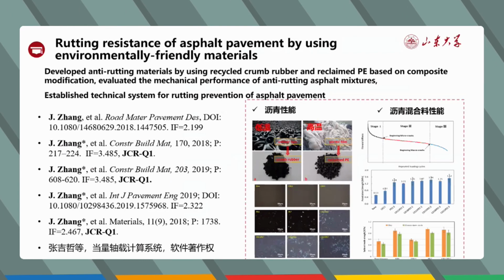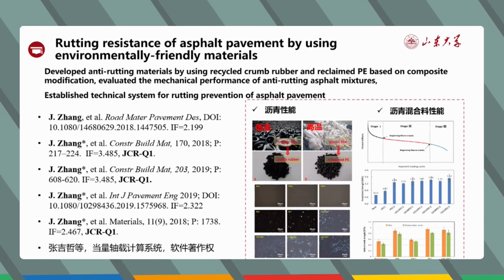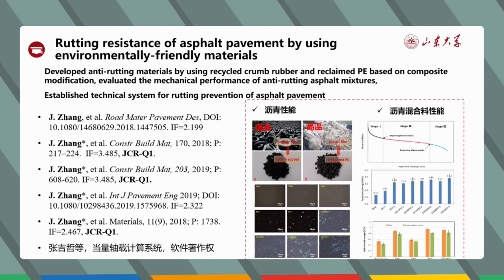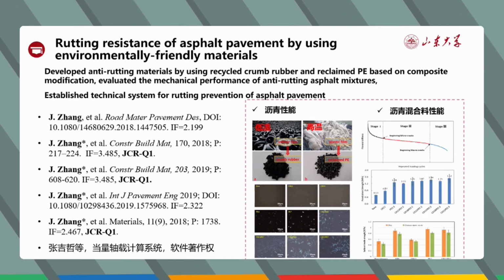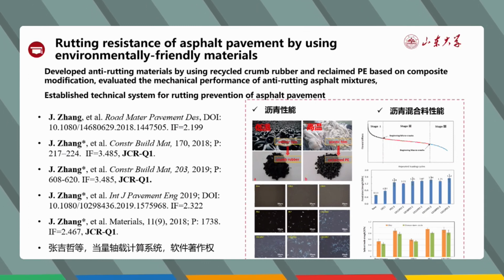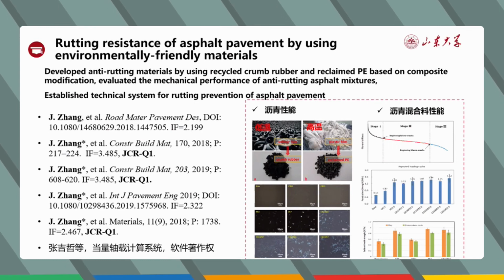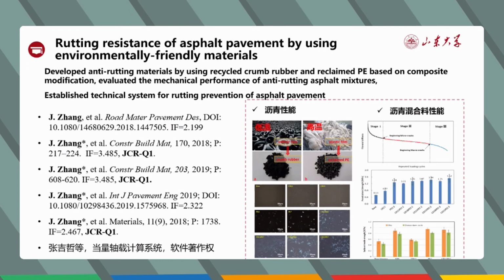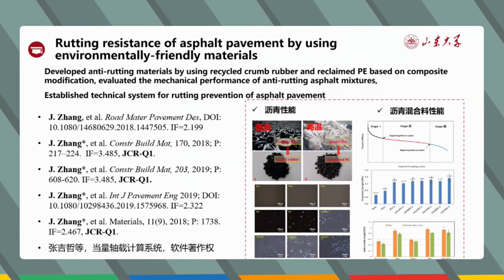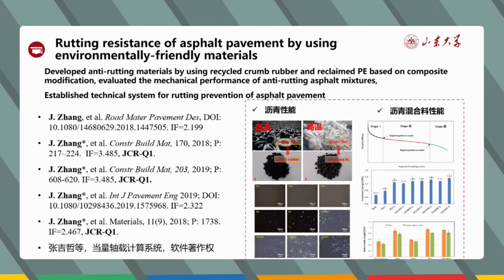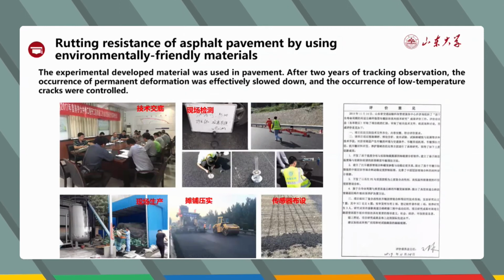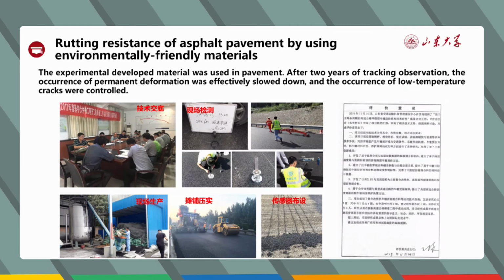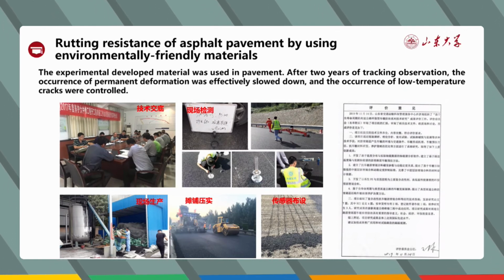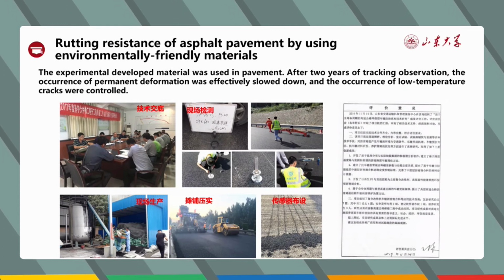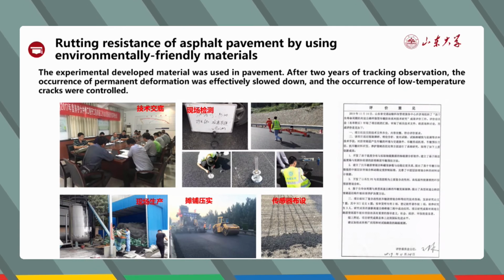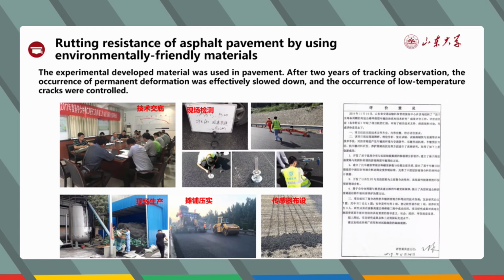The second one is the rutting resistance of asphalt pavement by using environmentally friendly materials. We developed anti-rutting materials by using recycled crumb rubber and reclaimed PE based on composite modification. We also evaluated the mechanical performance of anti-rutting asphalt mixtures. Because of this, we established the technical system for rutting prevention of asphalt pavement. We also used our developed materials in pavement construction. After 2 years of tracking observation, the occurrence of permanent deformation was effectively slowed down, and the occurrence of low temperature cracking was controlled. This proves that the developed materials are very good.